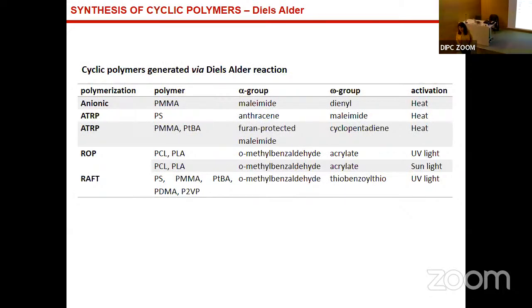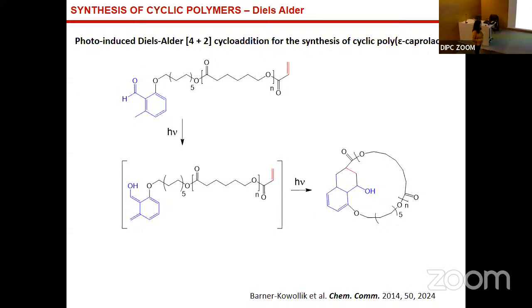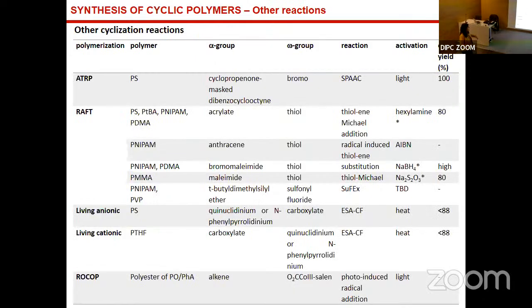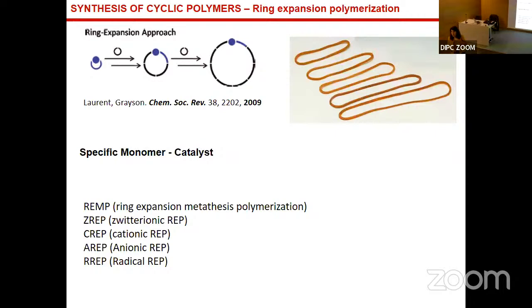Diels-Alder reaction, very common in organic chemistry, has been also very useful in the synthesis of cyclic polymers by using heat. And after this first example, then UV light was used for the generation of these cyclic polymers. This work was done by Barner-Kowollik in 2014, and he implemented the use of this group, which by activation with light forms this diene, and that reacted under the light conditions with the alkene group and closed the chain and formed the cyclic polymer. Many examples in the literature about the use of these and other reactions. I will not stop here because there are so many reactions, many words, but only to show you that there are many examples in the literature.